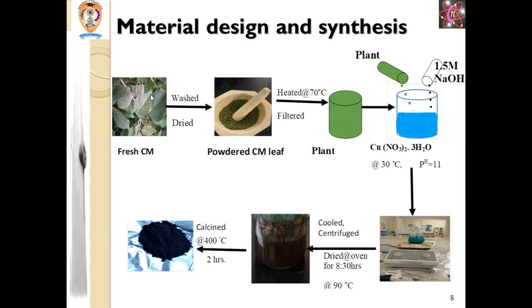So we have the plant, and the plant was washed, then dried and powdered. This powder was treated at 70 degrees C and filtered to prepare the precursor solution. This was mixed with copper nitrate solution, and sodium hydroxide was added for a fast reaction at 30 degrees C and pH 11. Then the solution was cooled, centrifuged, and dried, and we obtained a powder, which was calcined at 400 degrees C for 2 hours, and finally we obtained pure copper oxide nanoparticles mediated by the plant species.